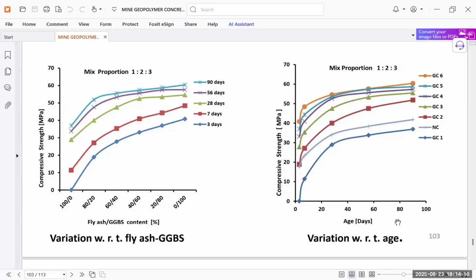And this is the variation with respect to age, which we are seeing. The compressive strength we will see in megapascal. So we can see this is NC, normal concrete, and this is GC1, GC2. You can get this as per different parts. This age variation is there. So we can see the normal strength is something like this, but in the geopolymer concrete variation, you can get strength more than this also as per the requirement.